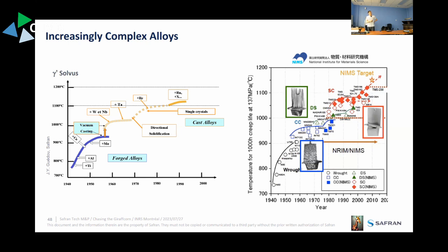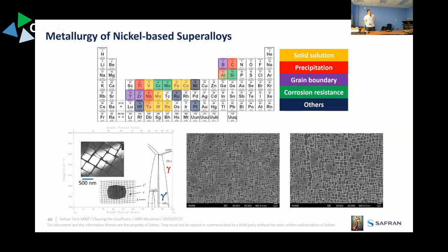So you align the grain boundaries to have better creep resistance. And then the next step was logically to remove completely the grain boundaries because they're detrimental to creep resistance. So it became the single crystal superalloys. And they are very different materials from other nickel-based superalloys. And this has some nice implications.